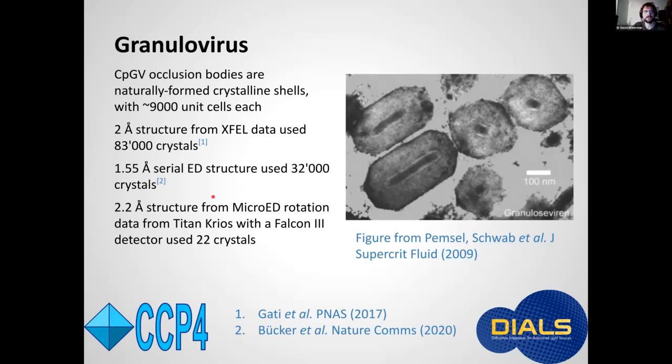Last year there was very impressive work producing a 1.55 angstrom structure by serial electron diffraction which required 32,000 crystals. But together with scientists from Thermo Fisher we solved the structure by rotation micro-ED and the data set is admittedly not as high quality as the other two but we only used 22 crystals.